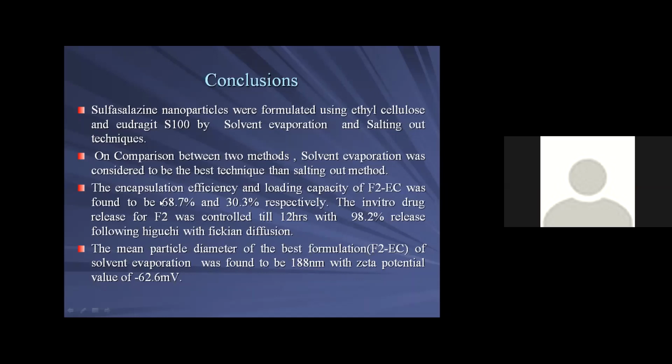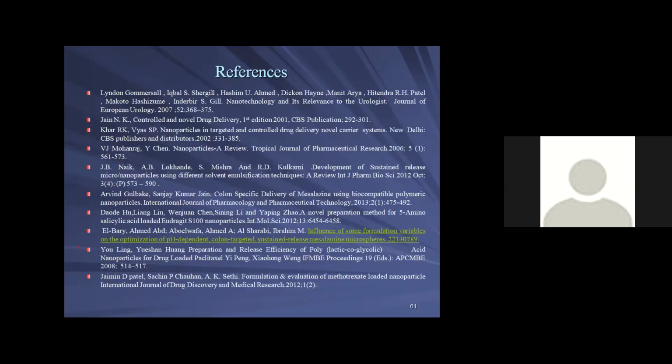So more trials have to be made in order to improve the entrapment efficiency of the formulation. When we compare both the techniques, both are exhibiting good results. In the salting out technique, we were able to obtain entrapment up to 70%. So in the salting out technique, entrapment efficiency is more, and mean particle diameter is better in the solvent evaporation technique.